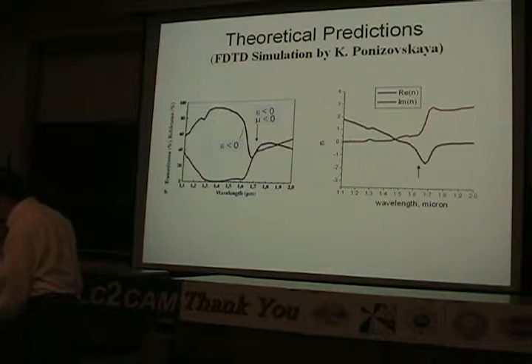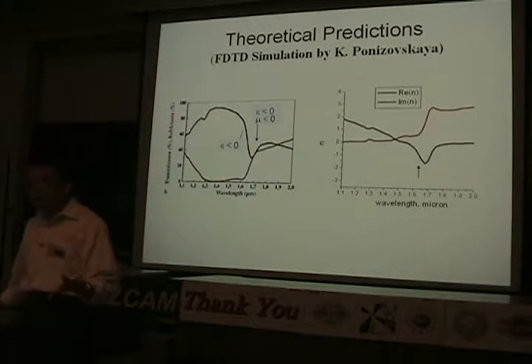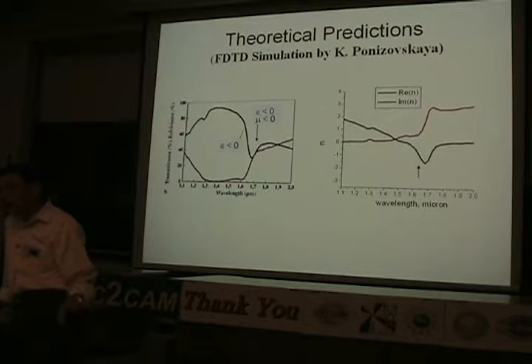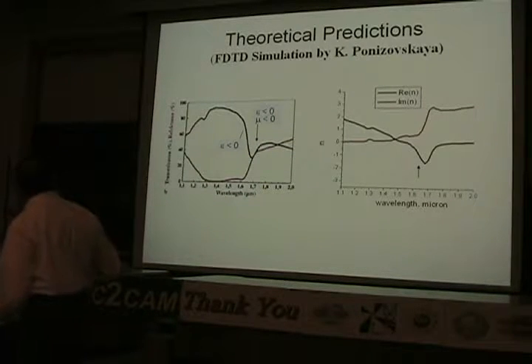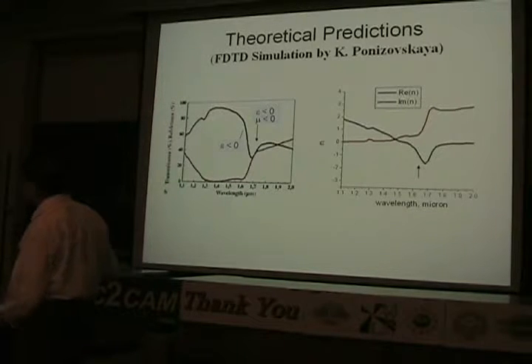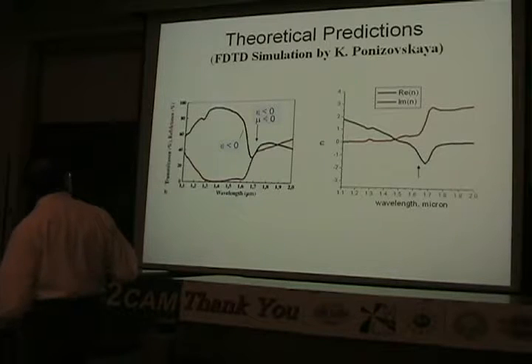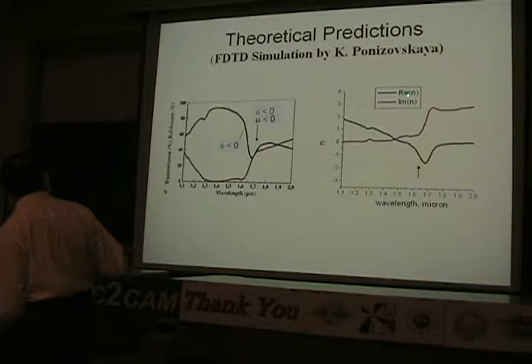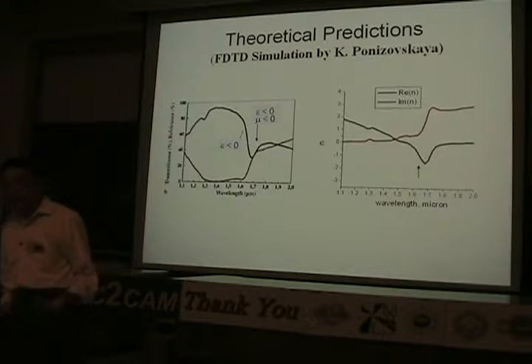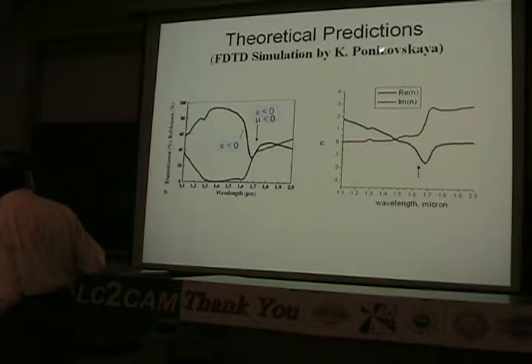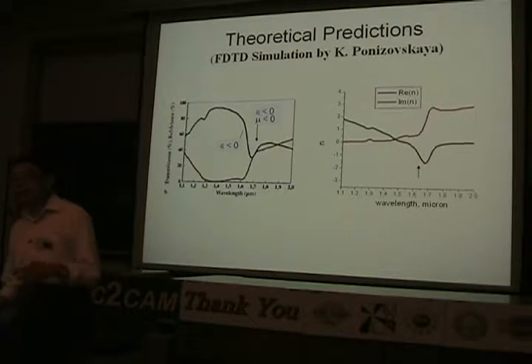So with this fishnet structure, you can do the numerical calculation to figure out the transmission of this layer and the reflectance of this layer. And then from that, you can deduce the real n and imaginary n. This was done by K. Ponizovskaya, and you can see that indeed we get a negative index in this region, which is close to the magnetic resonance.